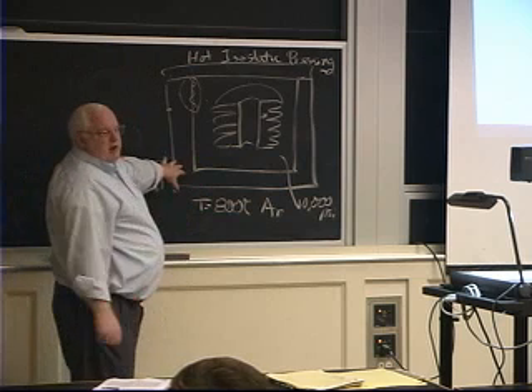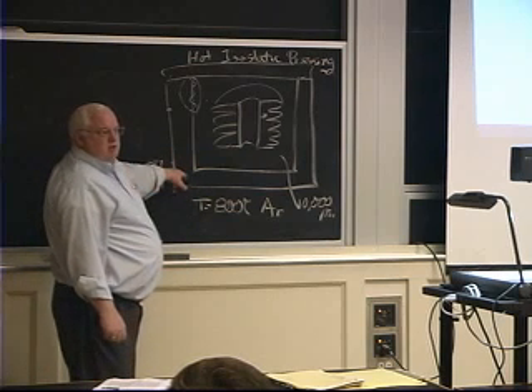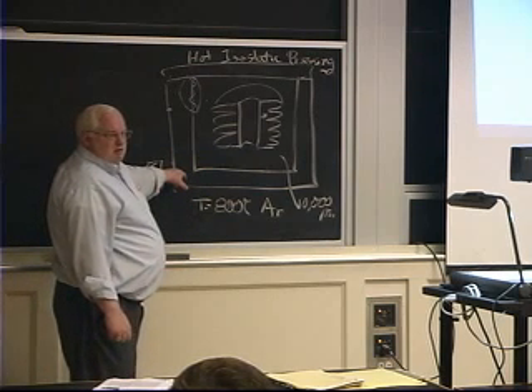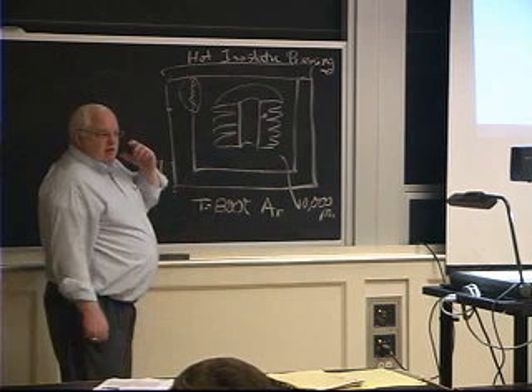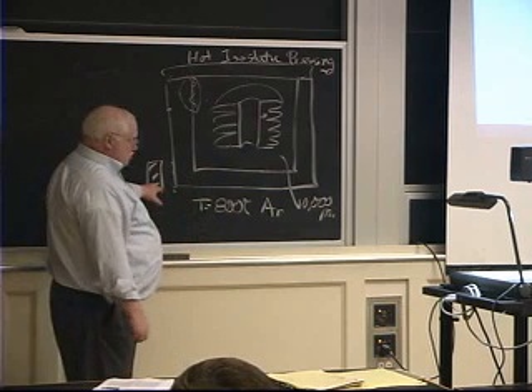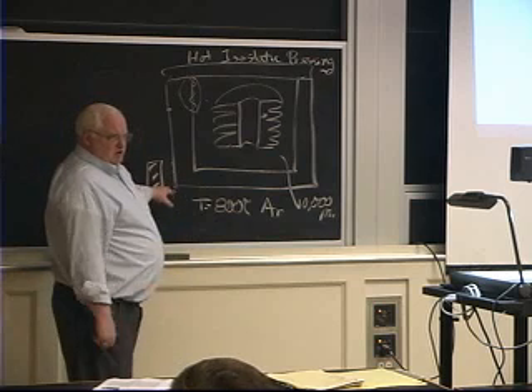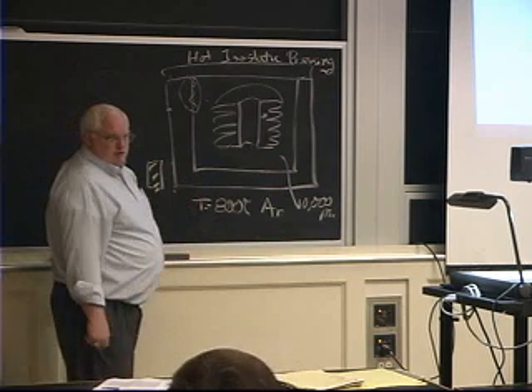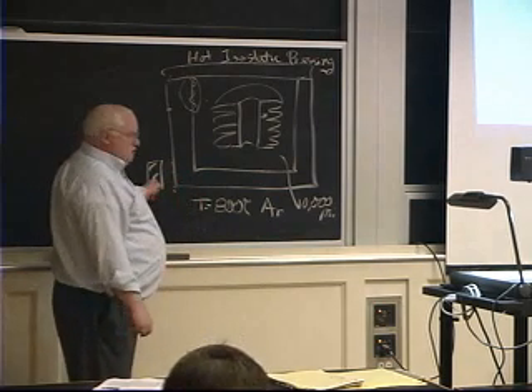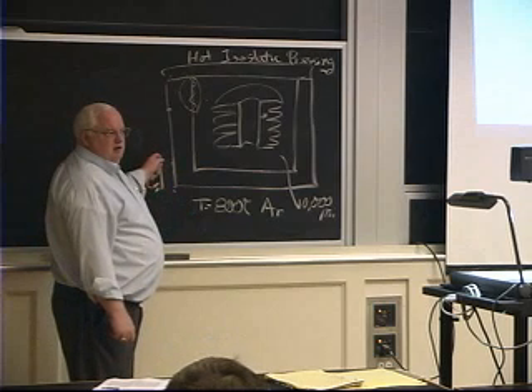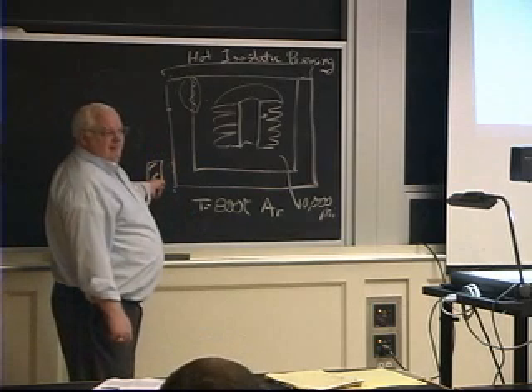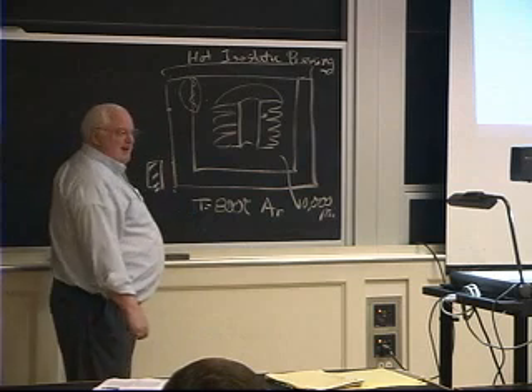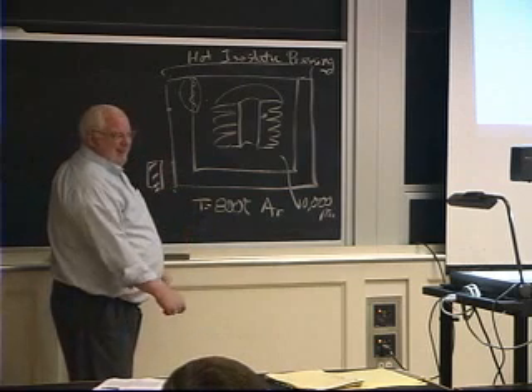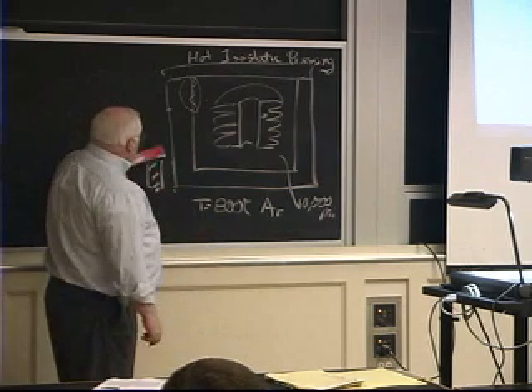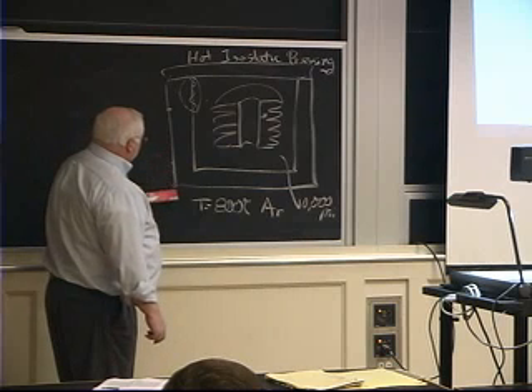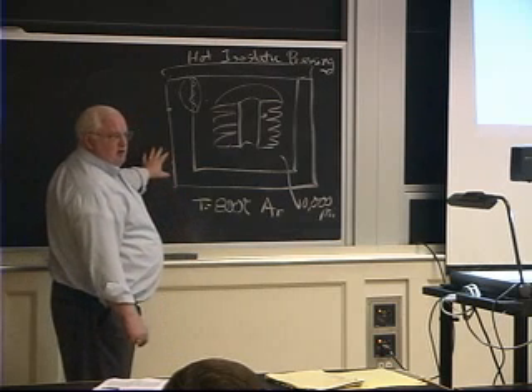But it's not as massive as that one. This might weigh 1,000 pounds. This one weighs 400,000 pounds. So they don't exactly heat up and cool down at the same rate. And so you just assume that this one went in the same furnace. You just sort of assume they all heated and cooled the same, except they don't. So this is one way that a heat treater can get you to pass spec the second time. They test a different size part. That's accepted by the codes because it's not the only thing you can do with an extractable part. I've seen several failures because of it.